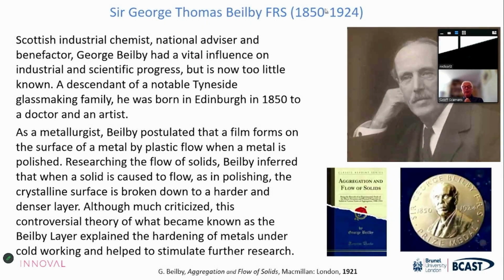In fact, they'd been found many years earlier. If you go back to almost the 1920s, they'd actually been discovered by George Beilby. And it was interesting that George Beilby came up during Stuart's talk, and there had been two Beilby medals awarded to people from within UMIST. But you can see that Beilby had already decided that something happened, interestingly, on the surface of metals subjected to things like plastic flow, particularly for polishing. And the only difference was he thought that the layers that formed during things like surface polishing were amorphous layers. And that's because of the power of the microscopes he had at the time, which was not enough to really establish that these were actually ultra-fine grained microstructures.